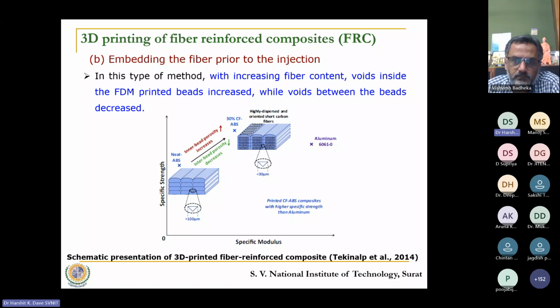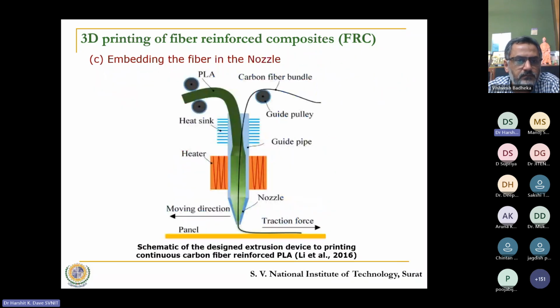Of course, it has to be ensured that the carbon fibers are oriented properly and they are properly dispersed within the filament, so that an even proportion of fiber can be observed all across the rasters within different layers of the part. So if we have the filament which is pre-mixed with carbon fiber, then that results in a good, strong part.